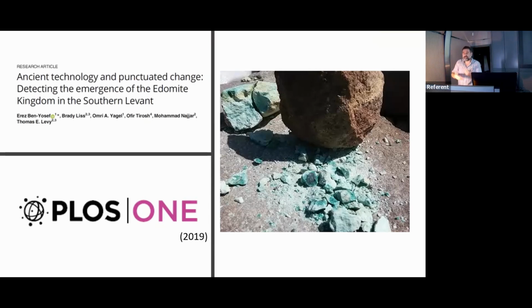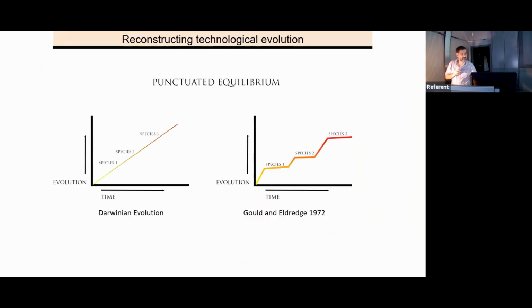They mixed it with the copper ore. It enabled the reduction of the smelting temperature, and it made the slag less viscous. So the separation between the metal and the slag is much better. Anyways, just remember that in this particular period, the smelting was really advanced and they were quite smart about it. And it is related to the results that we have.